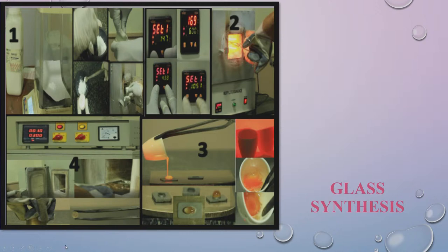Because in the morning you had that question, what happens if water molecules are present inside the glass matrix? To avoid them, to avoid the hygroscopic nature, we set it at 150 degrees and hold the temperature for 25 or 30 minutes so that water molecules get expelled. Then again, we set it at 438 degrees Celsius. This is to expel chlorides present in the precursors, the dopant precursors. Going to 600 is to expel carbonates. Then 1050 is the melting temperature of these glasses.